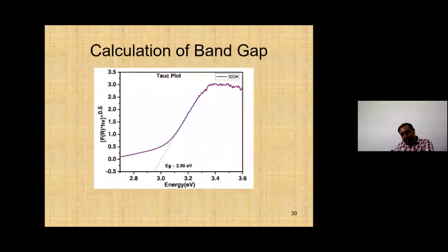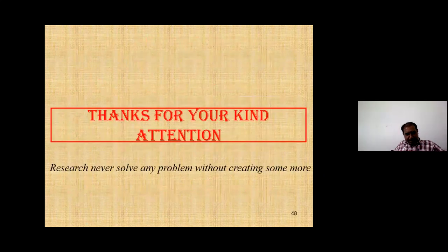I'll go to the next question. Yeah, please. How to indicate the type of defects from electronic transition taking place in the sample? Actually, using optical absorption spectroscopy, you cannot identify the type of defect, whether it is a point defect or due to dislocation, something like that. But what you can essentially say is that if you can see the tail state, it is due to the spread in the value of the lattice parameter, and this spread is assumed to be due to some type of disorder or defects present in the sample. But you cannot say that this particular tail is due to this type of defect. So you cannot identify defects using optical absorption spectroscopy, whether it is a Frenkel defect, a point defect, or a dislocation. You cannot do that.